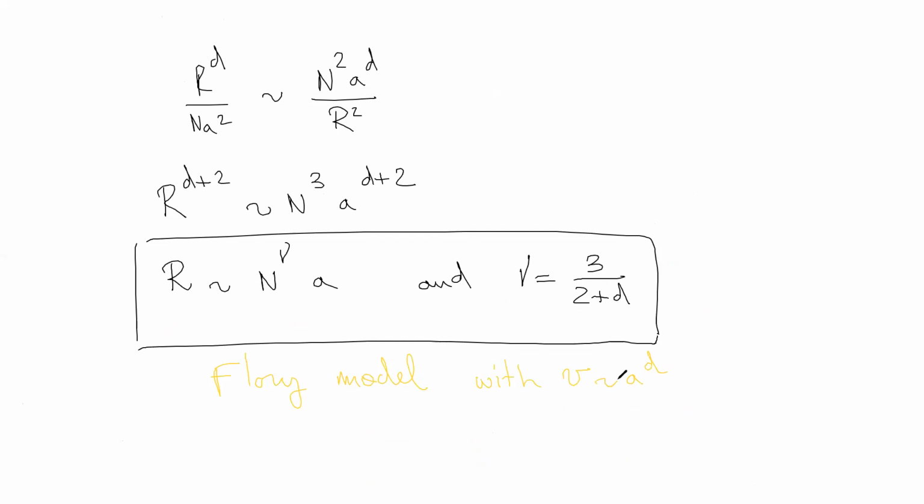Okay. So in a sense, what we did when we avoided any self-connection in the random walk, so really we were shooting for random walks, and each time there was an overlap, we rejected the walk, so that we left only the self-avoiding random walks. By doing that, we get the proper exponent proposed by Flory in his phenomenological approach, and we get another thing, which is that we now have a physical intuition on what the excluded volume is, what the parameter in the energy of Flory is. And now we say that, well, it's typically the size of a monomer.